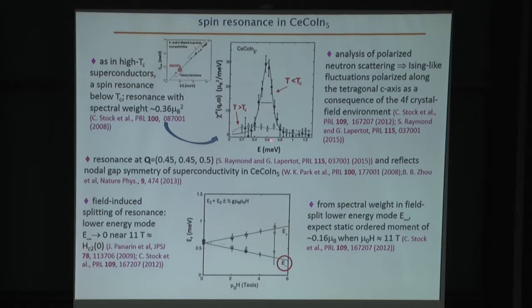The ratio of this resonance energy to the superconducting gap is precisely the same as that ratio found in other materials. I apologize you can't see this so well here, but these are resonance energy versus energy gap for both electron and hole doped cuprates as well as some iron pnictides. So polarized neutron scattering experiments show that the fluctuations in the spin resonance have Ising-like symmetry. They're polarized along the tetragonal c-axis of cerium-cobalt-indium-5. And this Ising-like symmetry is a consequence of the 4f crystal field environment.